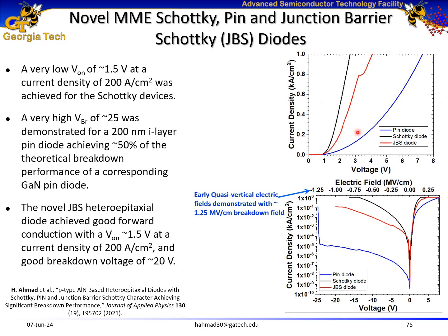Here I am showing the JV characteristics, both forward and reverse, of these diodes. These are representative figures. We see that for the Schottky diodes, we observe low turn-on voltage, but also low breakdown performance. For the pin diodes, we see high turn-on voltage and high breakdown performance. And for the junction barrier Schottky diodes, we achieve a low turn-on voltage of 1.5 volts and a high breakdown voltage of approximately 20 volts.